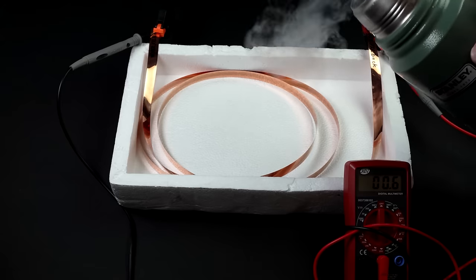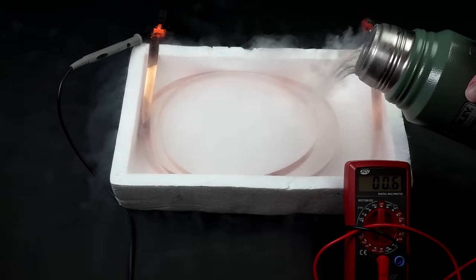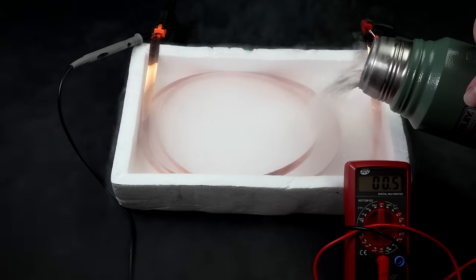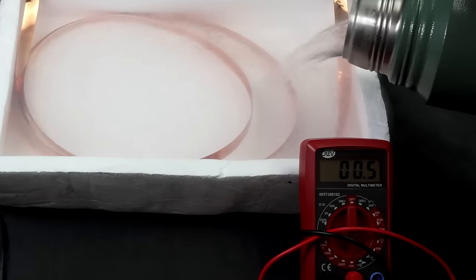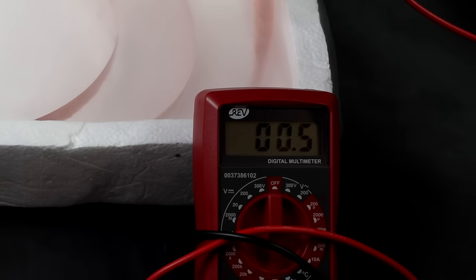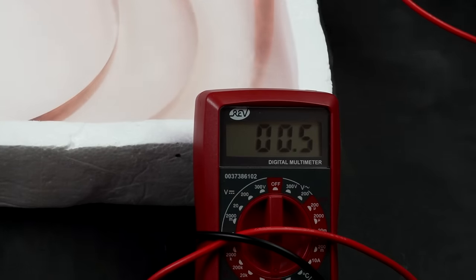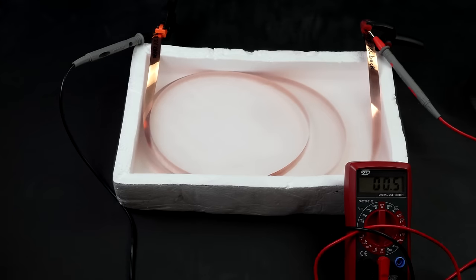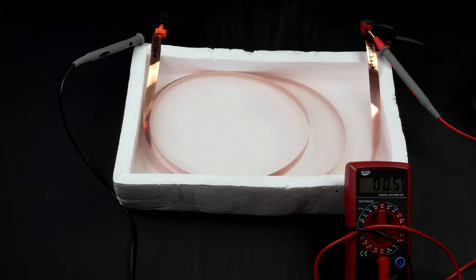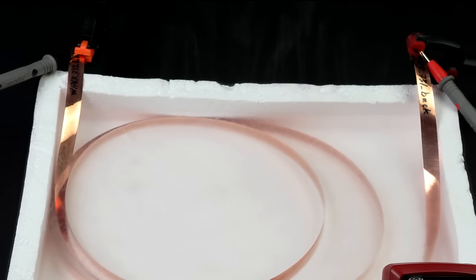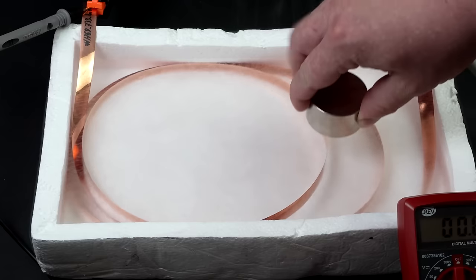When cooled with liquid nitrogen, it also loses all of its electrical resistance. And I tried to measure it with a multimeter, but for some reason, it showed almost the same values before and after the cooling. Probably because the tape itself is covered with copper, and the multimeter probes never touched the superconductor itself. Anyway, after cooling, the superconductor tape was trying to jump out of the foam box when I brought